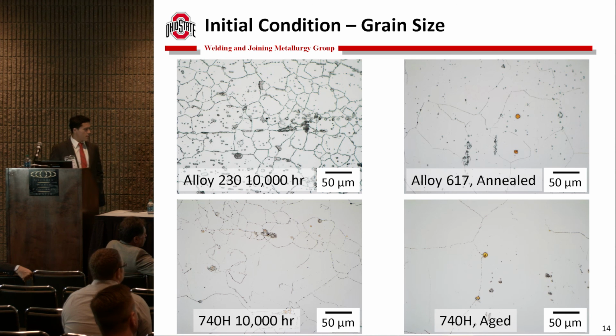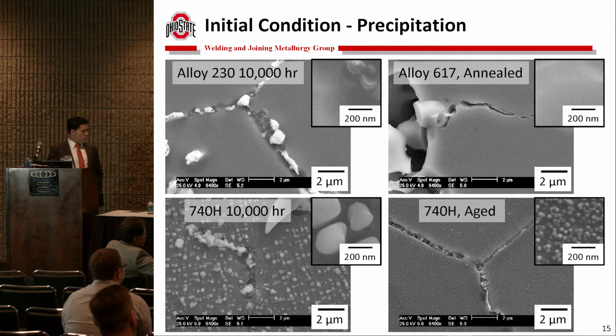So this alloy had a much coarser gamma prime and a bimodal distribution of grain size. So here's an example of the precipitation. There's simply tons of carbides in alloy 230. Alloy 617 starts out without any gamma prime. The 740H has a really uniform distribution of very fine gamma prime, and in the 740H pre-aged for 10,000 hours, of course they're very coarse cuboidal gamma prime.